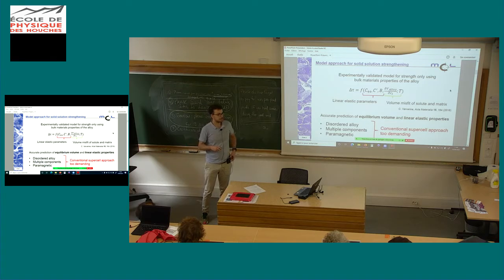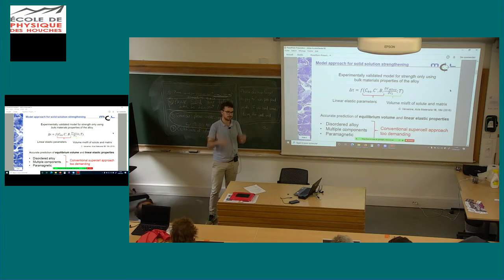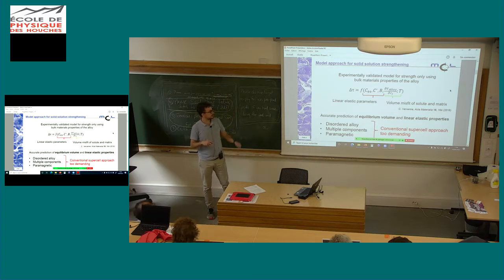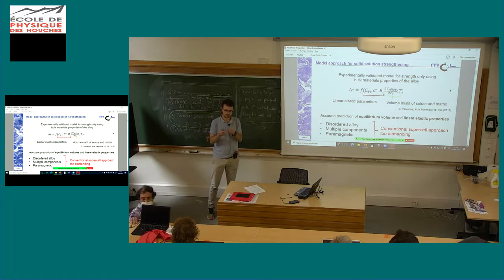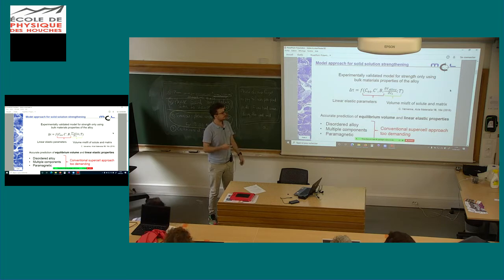So what we are doing now is to use an experimentally validated model for the strength, which only takes into account bulk material properties of our alloy. We just need linear elastic properties, and we need some kind of dependency of the equilibrium volume of our alloy with respect to the changes of the concentration of its components. And this is a measure for the volume misfit of the solute in the matrix. Of course, we can measure it, but we want to calculate it.